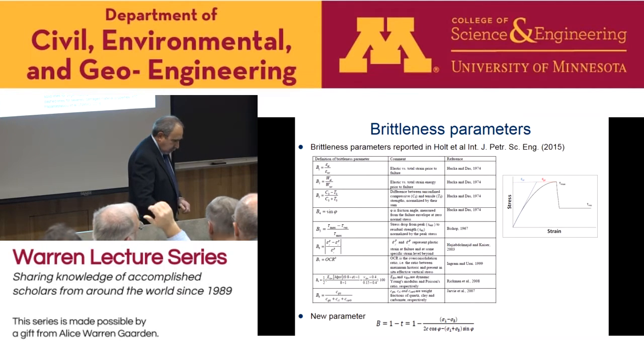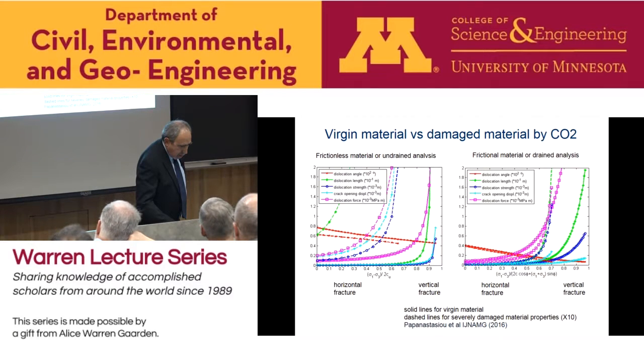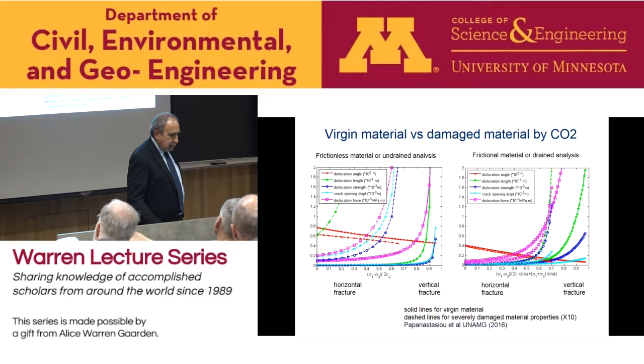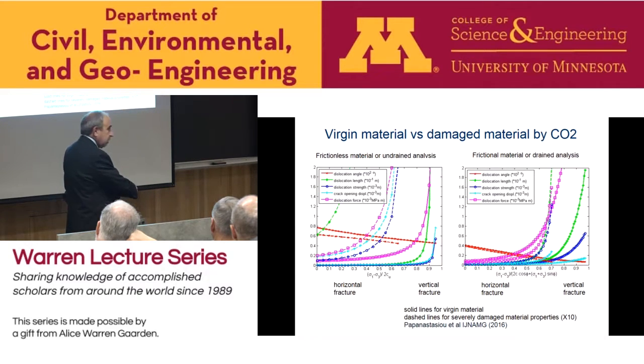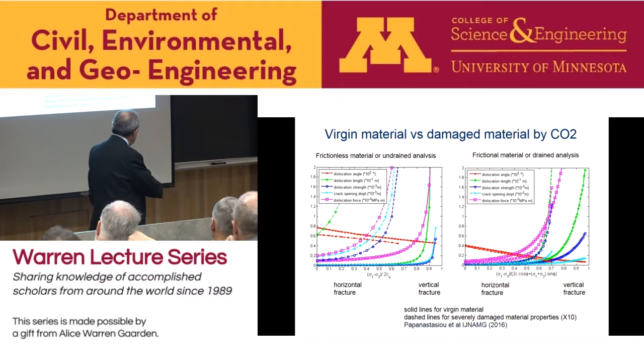Okay, I think I'm doing okay with the time. Now, we tried also to do some simple calculations, looking into the CO2 geological storage again, and what will happen to the results I presented before if the material parameters are damaged by the corrosive action of the CO2. CO2 is corrosive. So we try to decrease these material parameters to the extreme degree by 10 times. I say that the cohesion will be decreased by 10 times. And the fracture toughness will be decreased by 10 times.